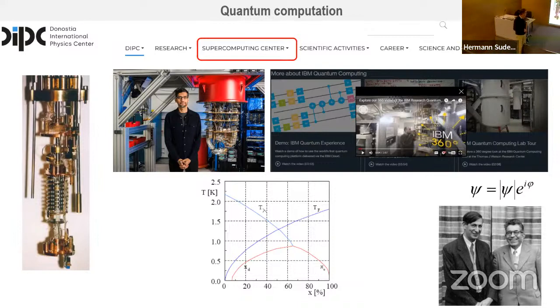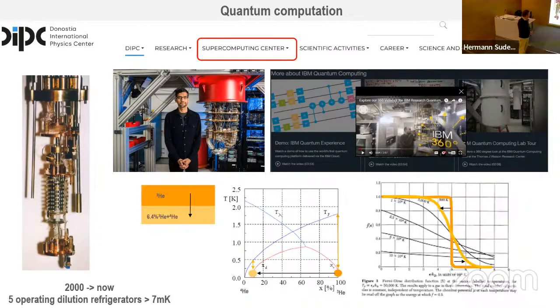Here you have pure helium 3, which has a relatively high Fermi temperature, around 1.8 Kelvin. So when you remove helium 3, the Fermi temperature changes and decreases. So the working principle of this machine is very simple. Here you have a Fermi gas, and if you place yourself here you will have the degenerate Fermi gas, so the Fermi function will be something like that. If you place yourself here, the Fermi function will be very much spread out. So if you manage to get atoms from here to here, you will force them into a high entropy state. And because they go into a high entropy state, they have to get the energy somewhere, and they cool. So it's a refrigerator. This is the operating principle of every refrigerator, but here it's a different one because you use the properties of a Fermi gas, that's all.